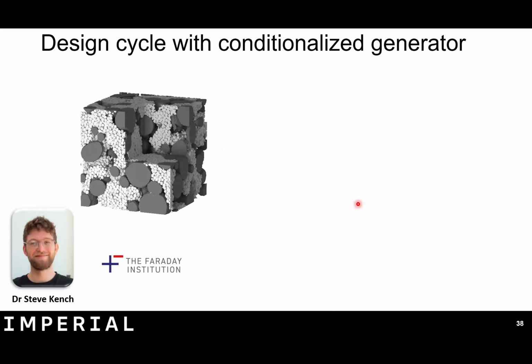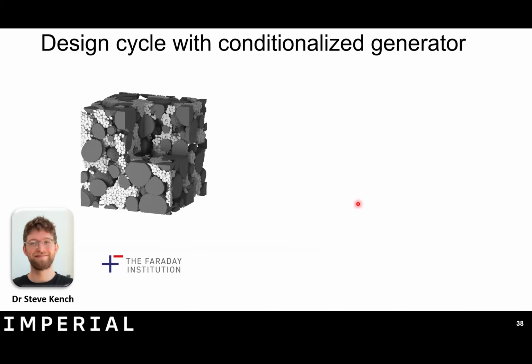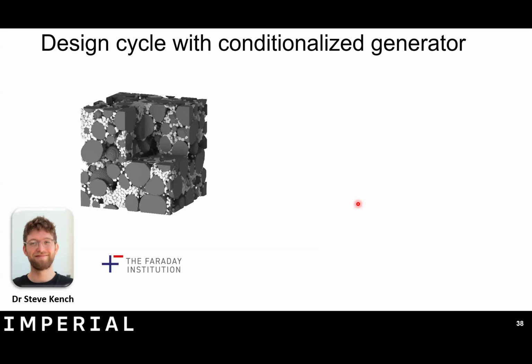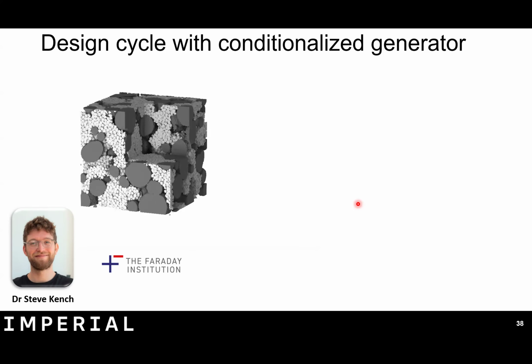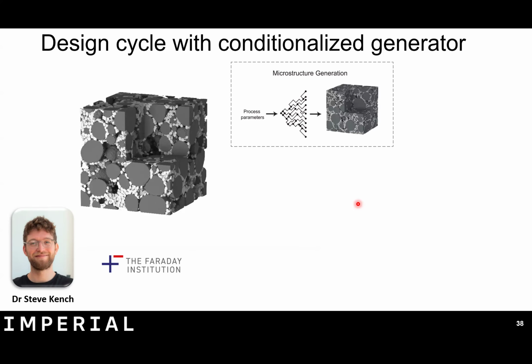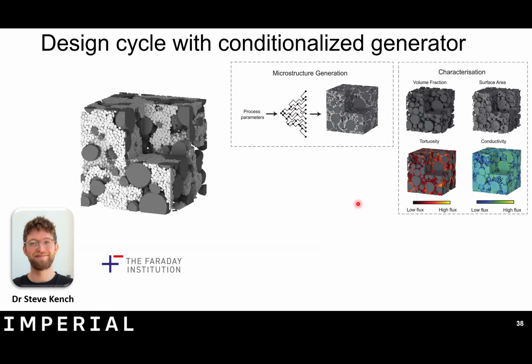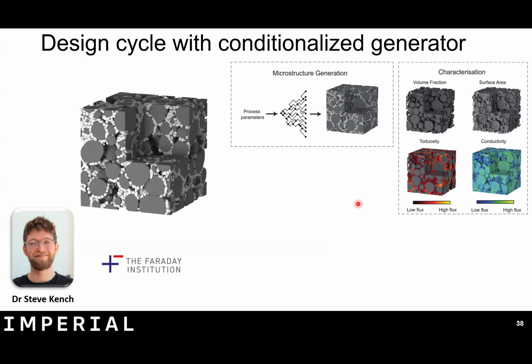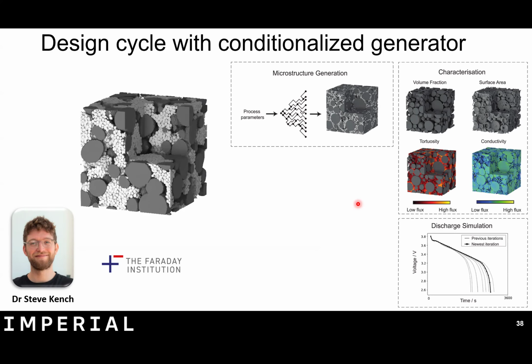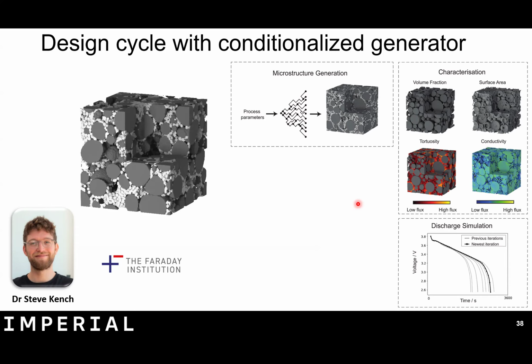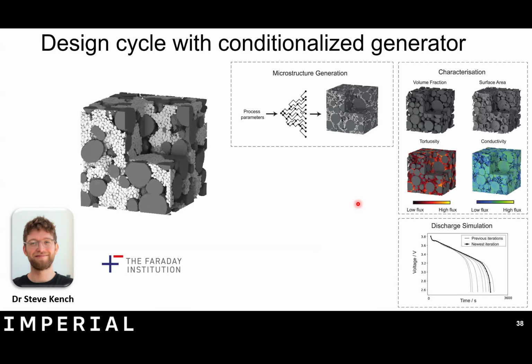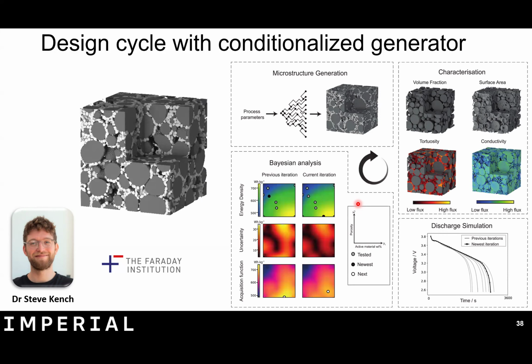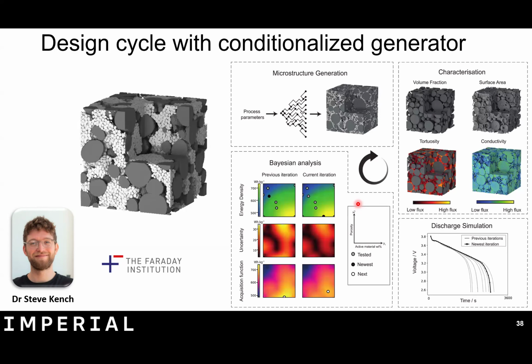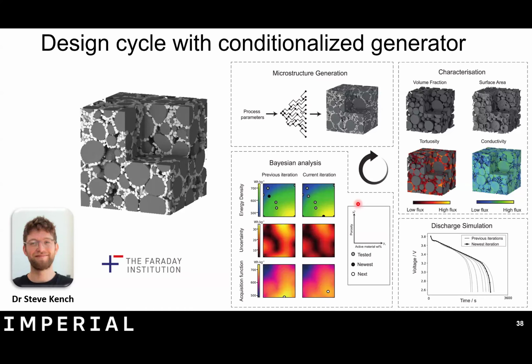Our approach instead has been to take SEM images of different electrodes produced using different manufacturing settings and use those to train a single conditionalized generative model of 3D microstructure. And once that model is trained, you can do inference in seconds, i.e. you can generate microstructure very quickly, pass those to metric extraction software like tau factor, and use those resulting metrics to parameterize discharge simulations in something like PyBaMM, and then ultimately use something like Bayesian optimization to search for optimized processing parameters for a particular desired battery specification.